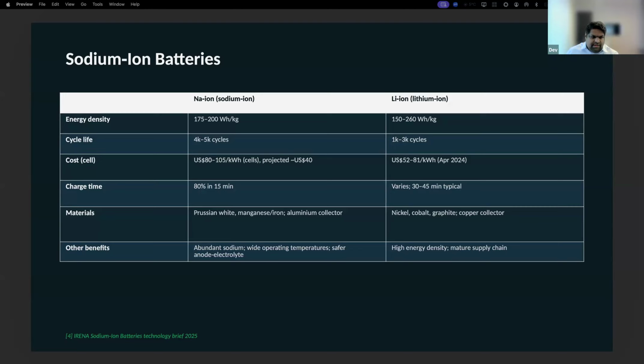Sodium ions are larger than lithium ions, making it harder to find stable host structures. Graphite is unsuitable for sodium ion anodes, so hard carbon derived from biomass or synthetic precursors is used. The research currently is focusing on improving cycle life and increasing energy density by optimizing cathode materials and electrolyte formulations.